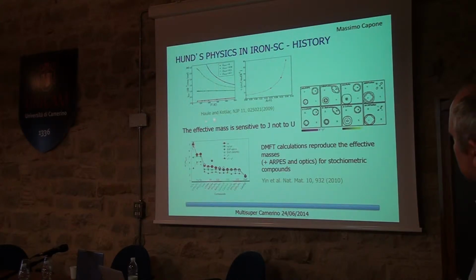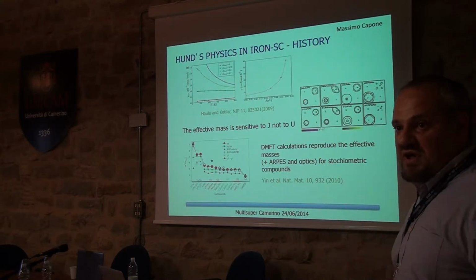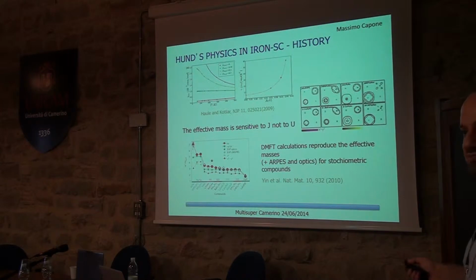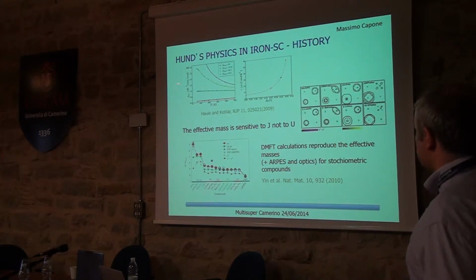This is the spin susceptibility, and this is the Sommerfeld coefficient, the prefactor of the linear term of the specific heat, which is associated essentially to the effective mass of the carriers. You see this increases a lot if you crank up the J interaction in a finite and reasonably small window of parameters. So it's very, very sensitive, while the same would not be true for the Hubbard U. This is an interesting observation.